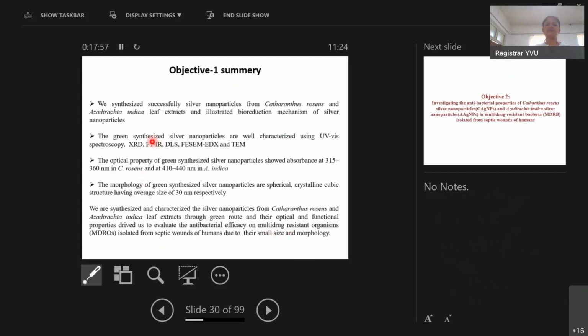This is my objective 1 summary. We successfully synthesized silver nanoparticles from Catharanthus roseus and Azadirachta indica leaf extracts and illustrated the bioreduction mechanism of silver nanoparticles. The green synthesized silver nanoparticles are well characterized using UV visible spectroscopy, X-ray diffraction analysis, Fourier transform infrared analysis, dynamic light scattering technique, field emission scanning electron microscope, EDAX, and transmission electron microscope. The optical property of green synthesized silver nanoparticles showed absorbance at 315 to 360 nanometers in Catharanthus roseus and at 410 to 440 nanometers in Azadirachta indica. The morphology of green synthesized silver nanoparticles is spherical, crystalline, cubic structure having average size of 30 nanometers respectively.